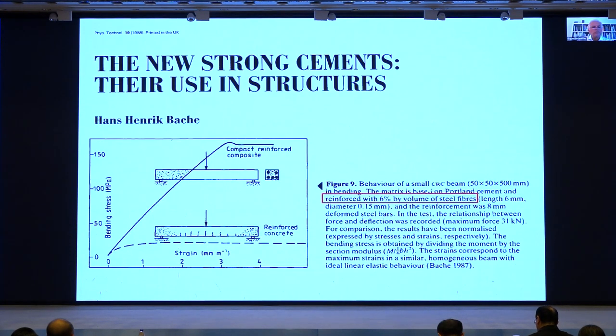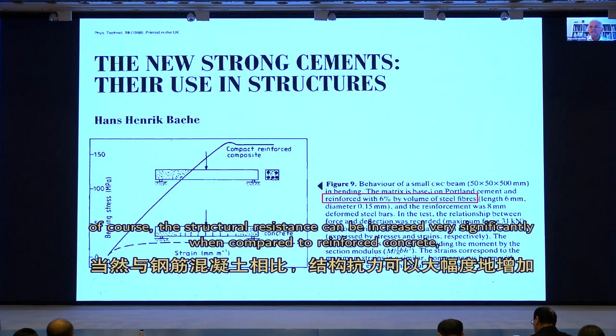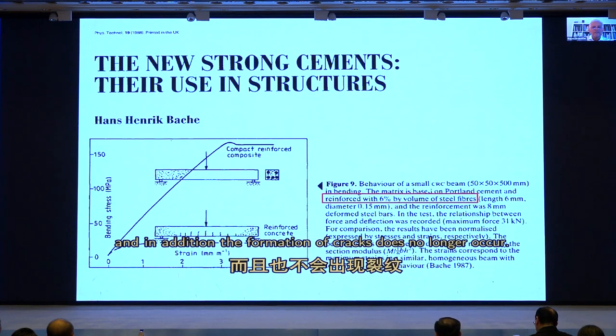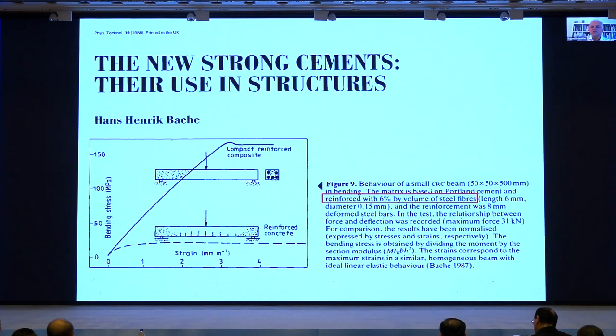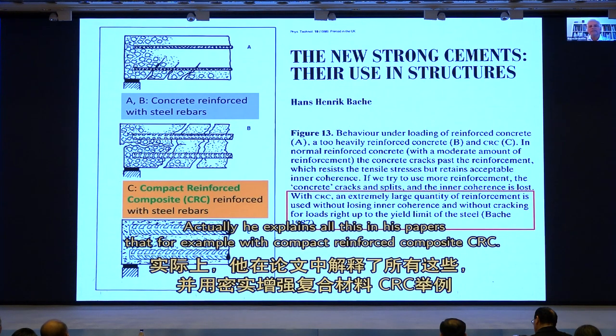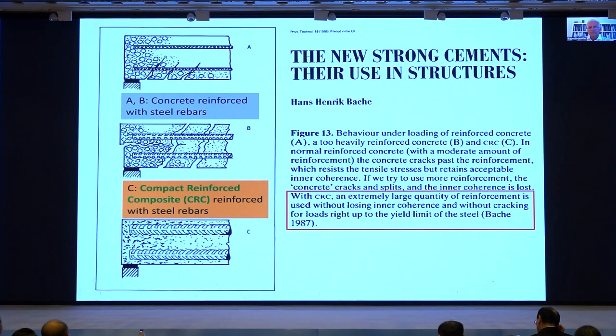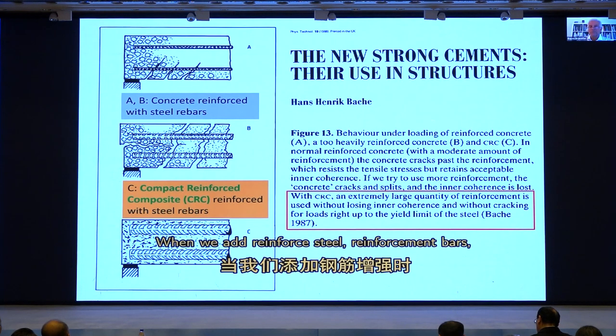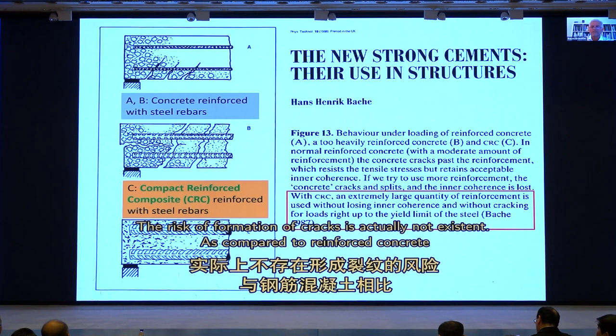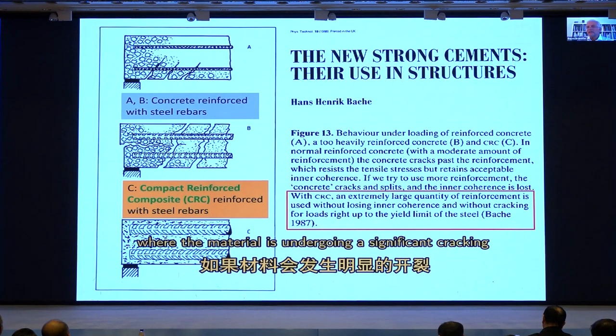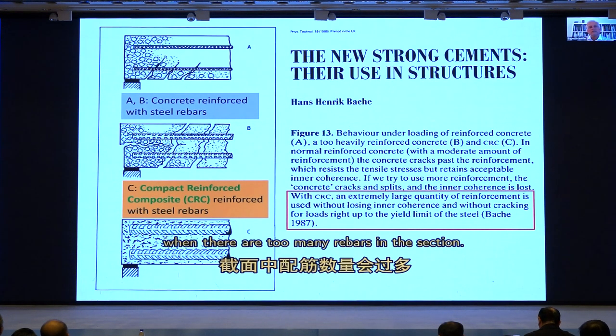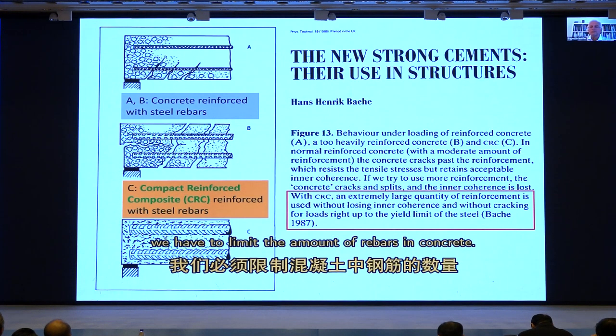And with this structural material, of course, the structural resistance can be increased very significantly when compared to reinforced concrete. And in addition, the formation of cracks does no longer occur. That was his message. Actually, he explains all this in his papers, that for example, with compact reinforced composite, CRC, when we add steel reinforcement bars, the risk of formation of cracks is actually not existent. As compared to reinforced concrete, where the material is undergoing significant cracking when there are too many rebars in the cross-section. Or in other words, we have to limit the amount of rebars in concrete.